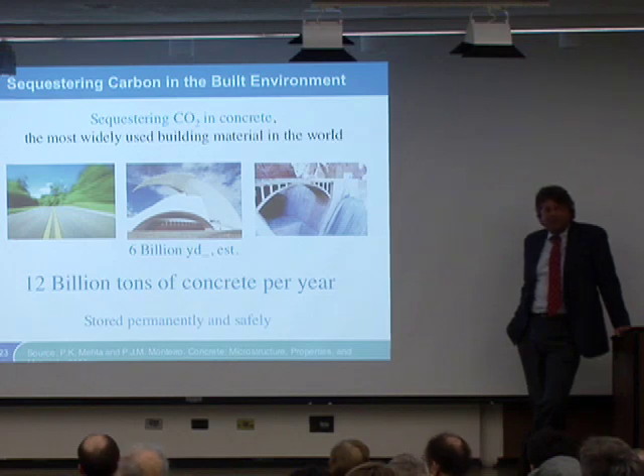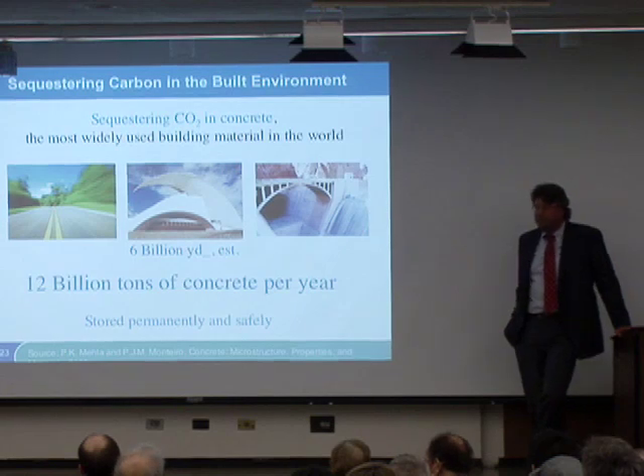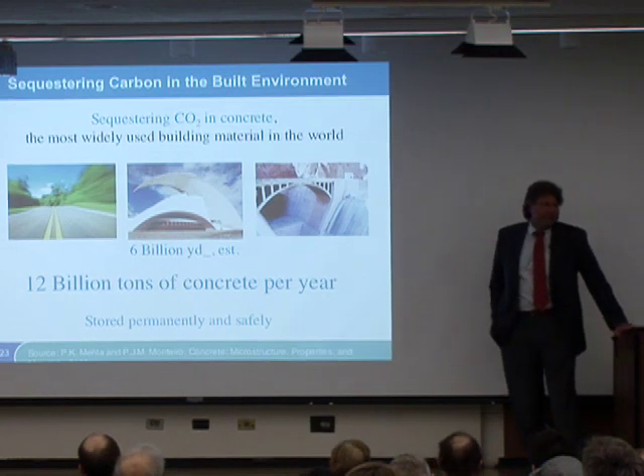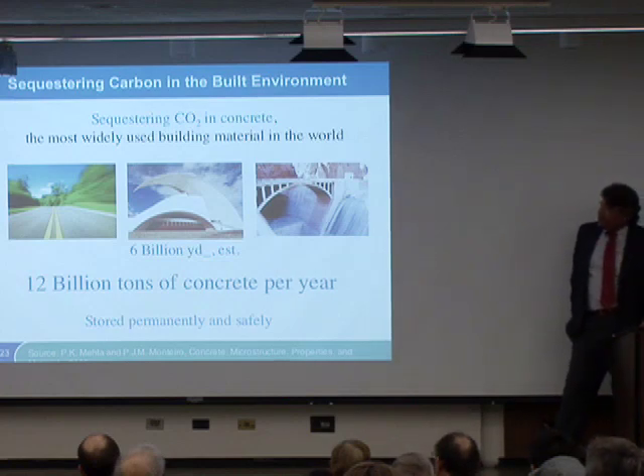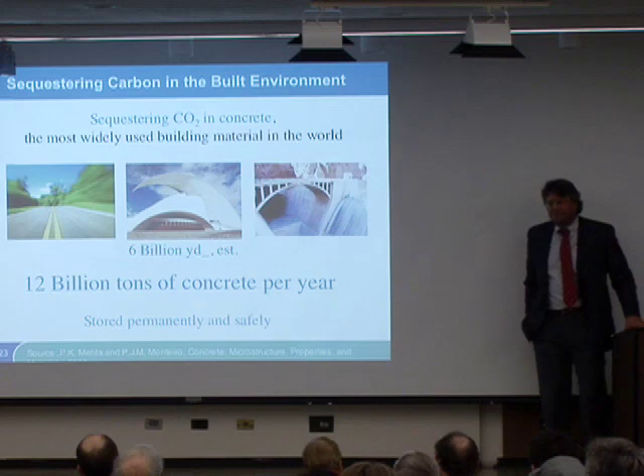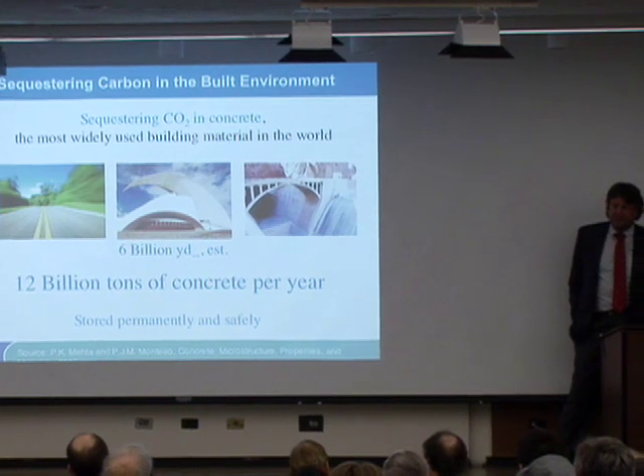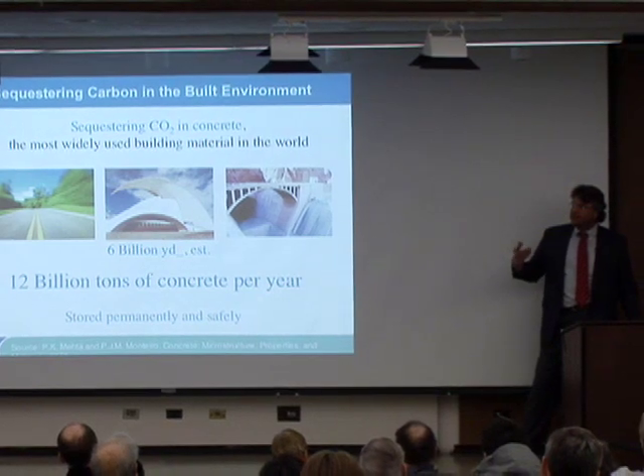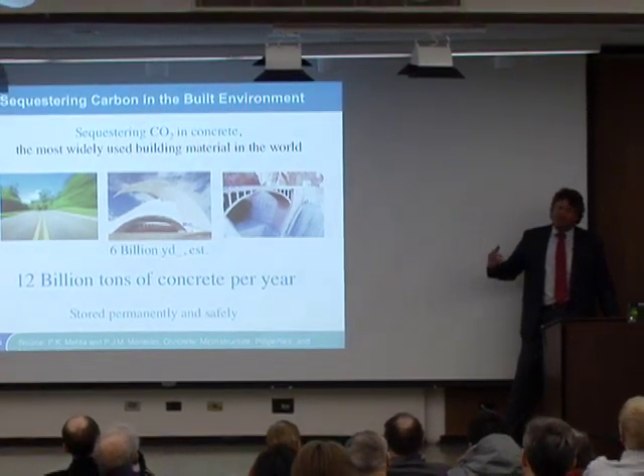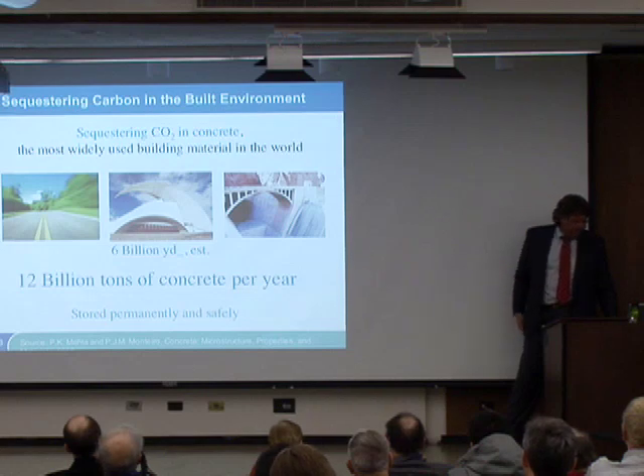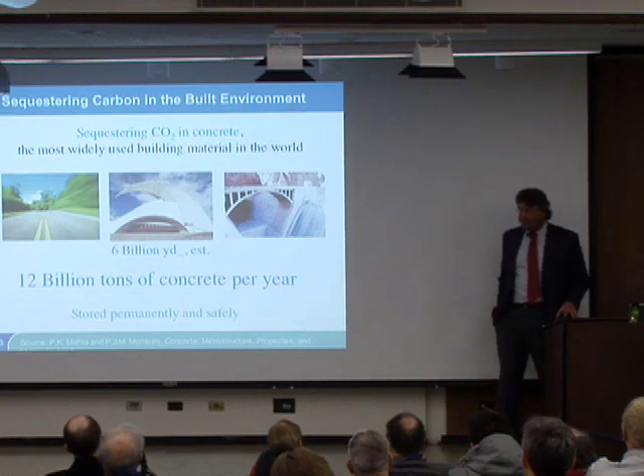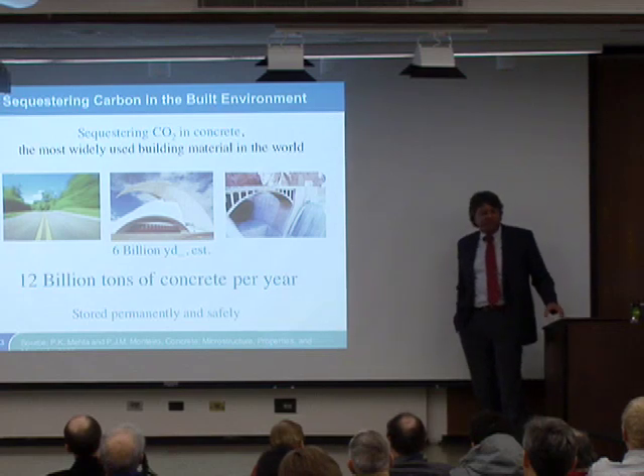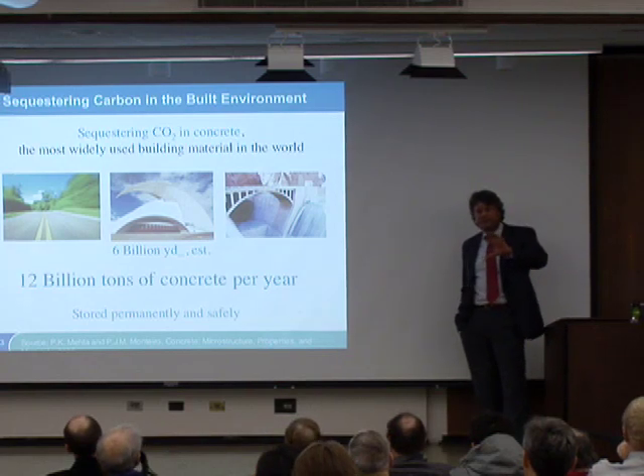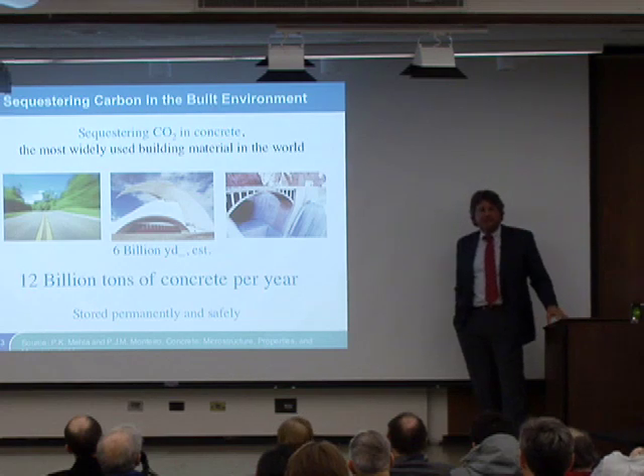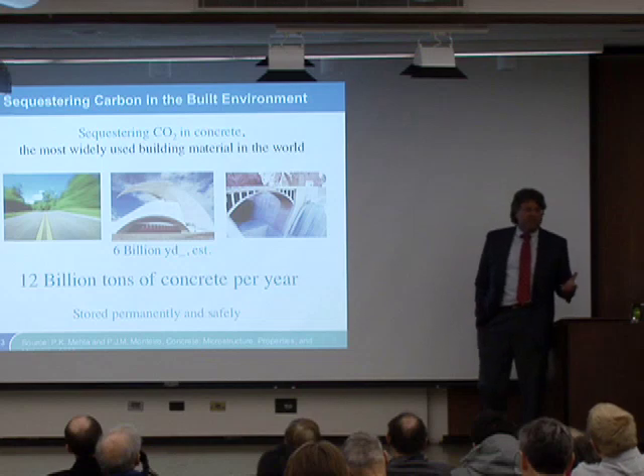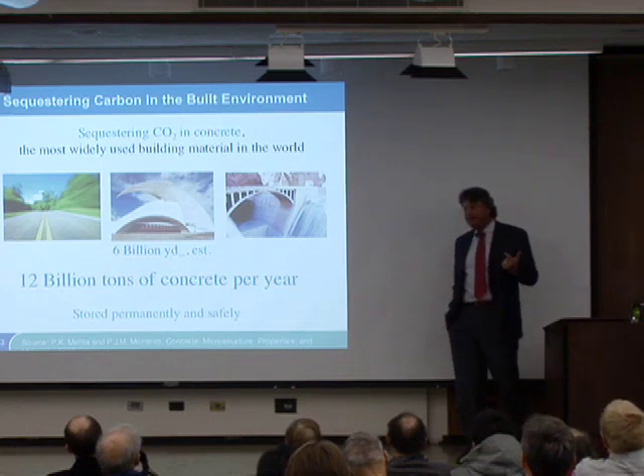If we used it in aggregate, you can multiply that times 20. And there'd still be need for more aggregate in all the materials. So it's of the order of magnitude that it's a place you could put it and it'd stay there. Carbonate minerals are carbonate CO3, so you're taking CO2 and making CO3. It's a very stable covalent complex. The only way to get the CO2 back out of it is with acid or very high heat.